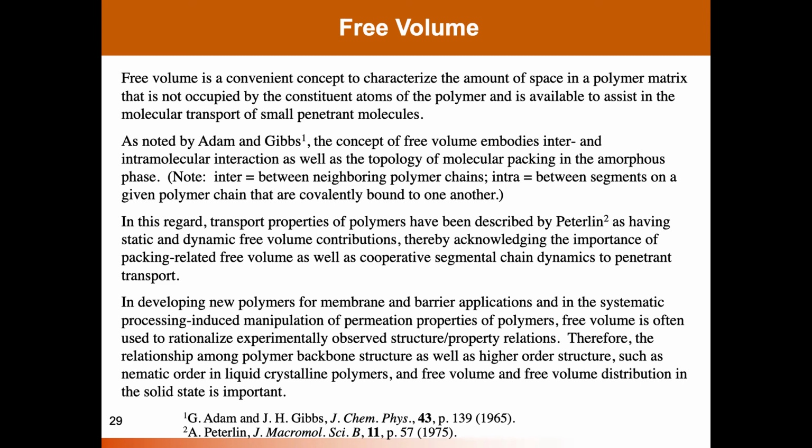Anton Petterlin talked about also the contributions of static and dynamic free volume. And so static free volume would be, okay, if you were to take a polymer and freeze it and not allow any molecular motion whatsoever, there would still be some regions in the material that were open space. And in principle, if you were a penetrant small enough, you could go through that topology without requiring any penetrant motion. That would be what Petterlin considered to be static free volume.